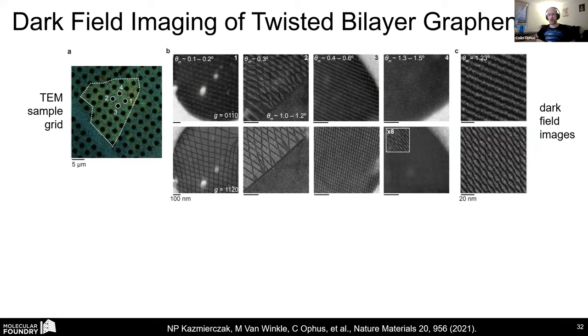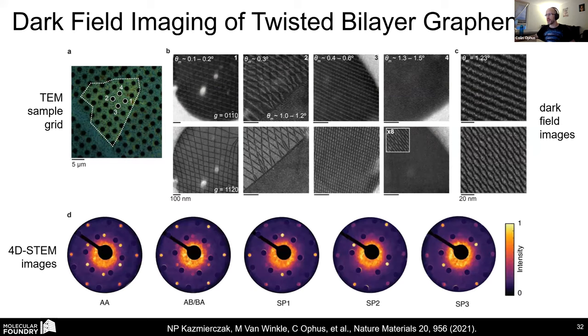The dark bands are where you get destructive interference between the lattice, and the bright bands are where you get constructive interference. So you can use dark field TEM to map out the lattice structure, but with 4D-STEM, we can go one step further here. So here are a couple different 4D-STEM images from our data set here, and it's sitting on a boron nitride substrate, which we've masked off in black dots.